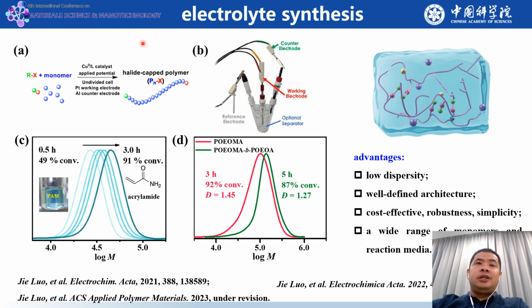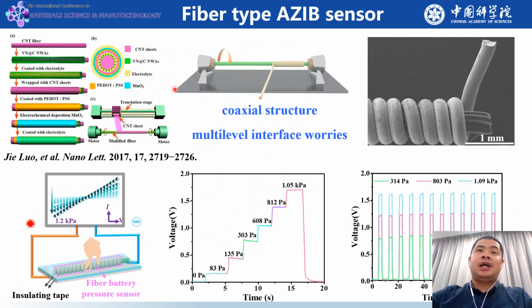In this project, we try to synthesize hydrogel electrolyte through simplified eATRP to construct a low dispersity and well-defined architecture polymer for preparing gel electrolyte. And we have obtained several valuable works cooperated with Padua University and University of Cordoba, Spain. In addition to the cathode and hydrogel electrolyte, another important step is the fiber device preparation.